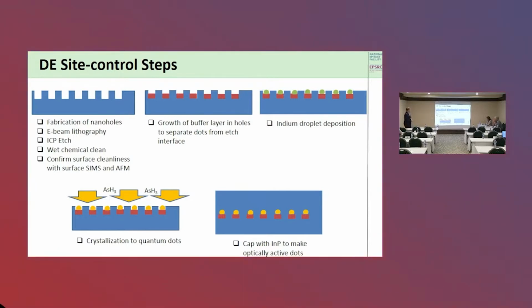Then we grow a buffer layer inside these nanoholes. That is to make sure that any dots that we grow are away from the etched surface, because the etched surfaces can cause noise. Then we deposit the indium, and we hope and expect that the indium will fall into these holes, and then we have site control of the indium droplets. Then we crystallize these droplets, and finally we cap with indium phosphide to make the quantum dots that we've formed into optically active quantum dots.